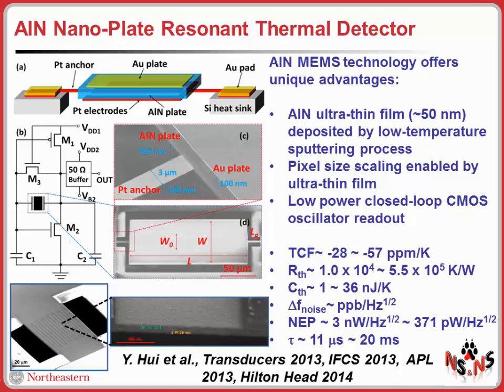But in general, for resonant sensors, scaling of the resonant device is a key element. And we can do that with aluminum nitride thin film, maintaining at the same time very good transduction capability. The piezoelectric properties of such thin film aluminum nitride are still maintained even in this reduced dimension. And thanks to high quality factor and large electromechanical coupling coefficient, the equivalent electrical impedance of this kind of device is quite low, and therefore this device can be directly connected in the feedback loop of a simple and low power sustaining amplifier. Here you see an example, which I'll show you later, of a very simple amplifier based on a 0.5 micron CMOS technology. This really enabled the implementation of resonant sensors that have high performance, but also with a low power electronic readout.